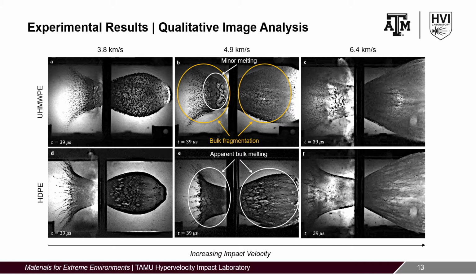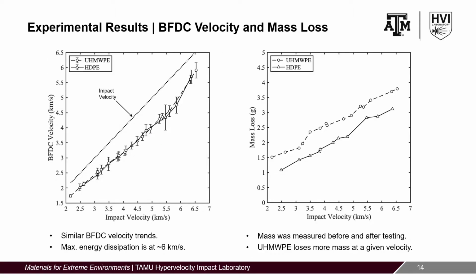It is also evident from these images that at a given impact velocity, the back face debris cloud of ultra-high molecular weight polyethylene and high-density polyethylene tend to be the same shape and size, while those of the front face debris clouds differ significantly. The leading edge velocity of the back face debris cloud was measured and averaged over its entire expansion. Here, the back face debris cloud velocity is plotted as a function of impact velocity.